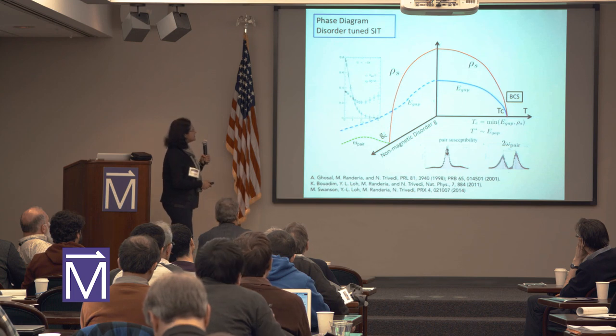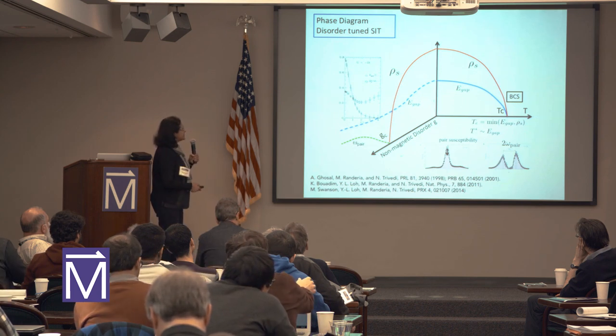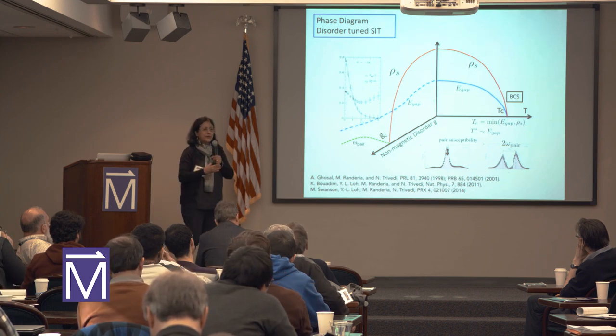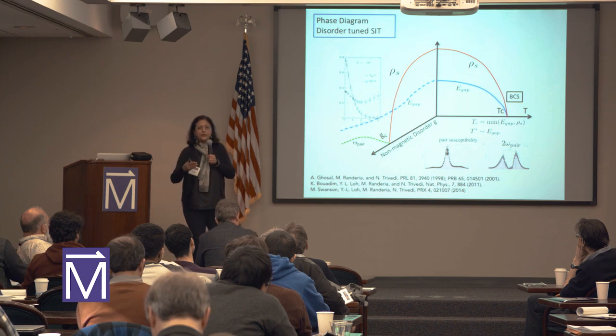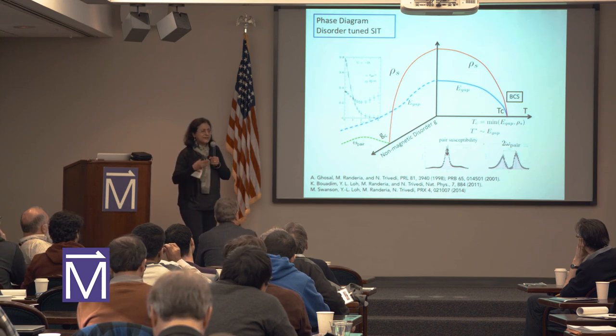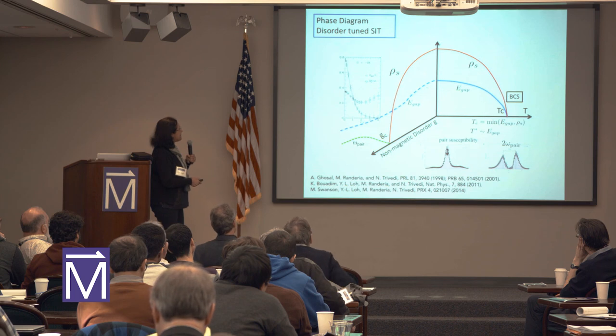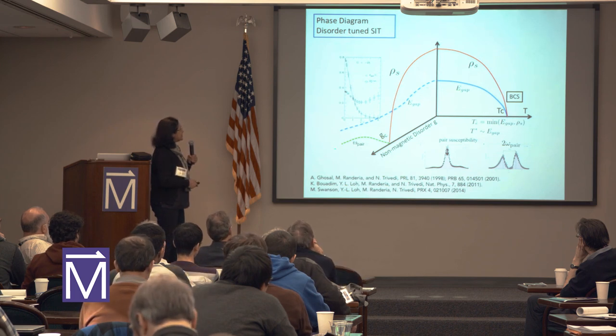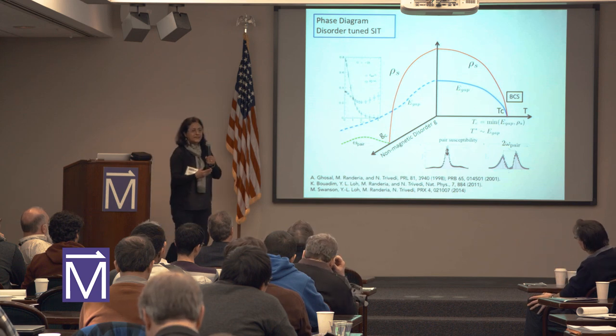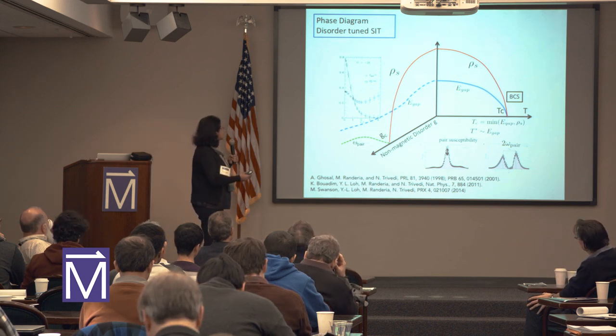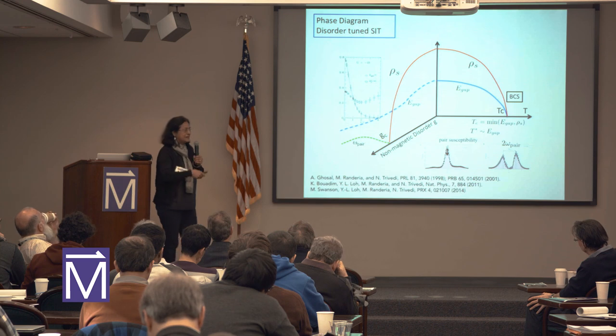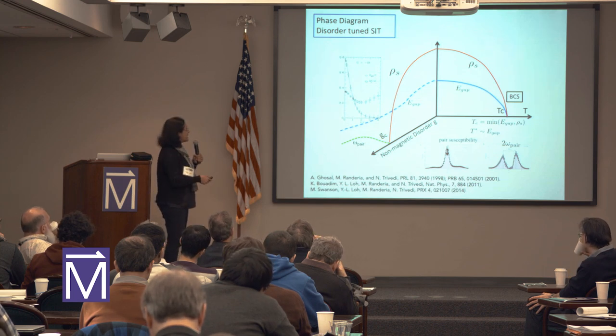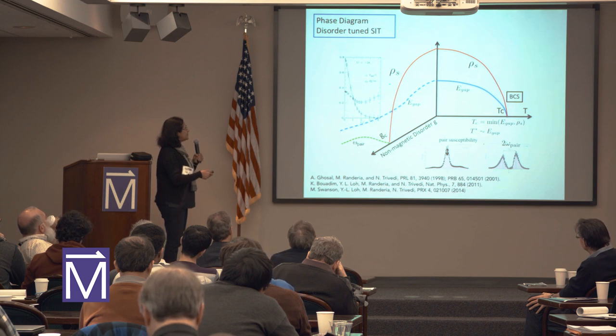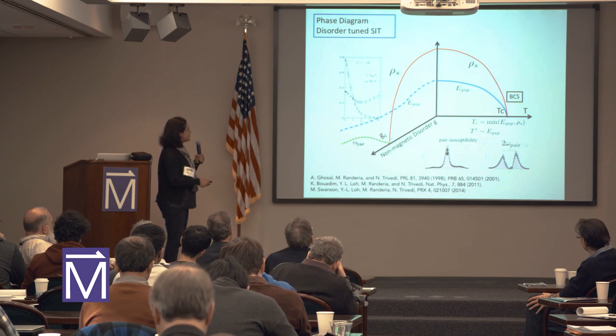Now, when you turn on disorder, what we found using this Bogoliubov-de Gennes method, where we kept the inhomogeneity in the order parameter and solved for it self-consistently, is that the gap remained finite all through. So in other words, there was no Anderson insulator with gapless excitations. In fact, the gap was finite for arbitrarily large disorder, but the superfluid stiffness vanished at some critical point.